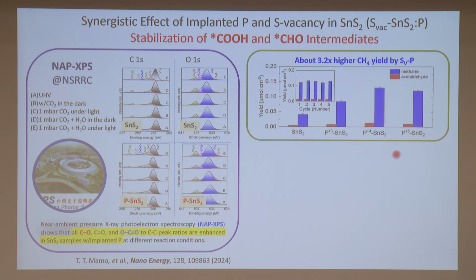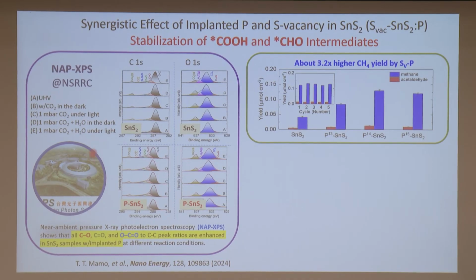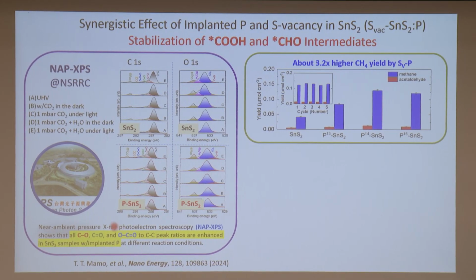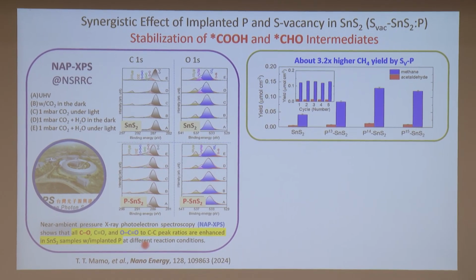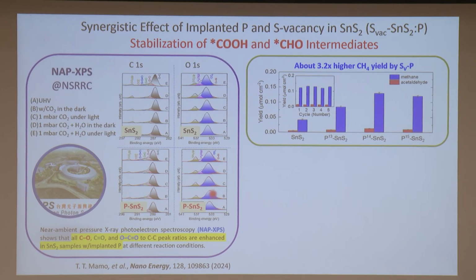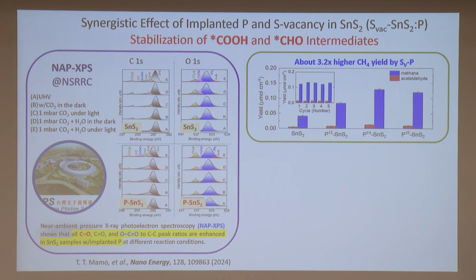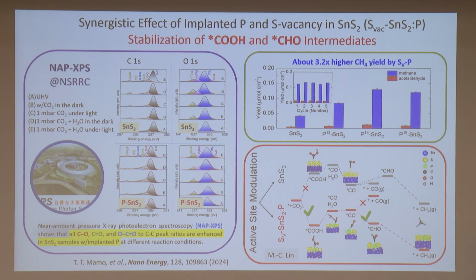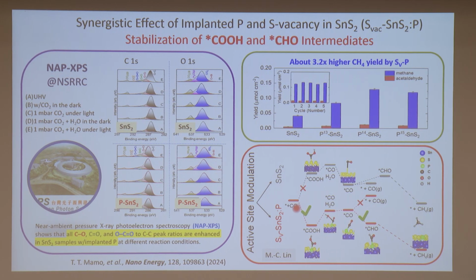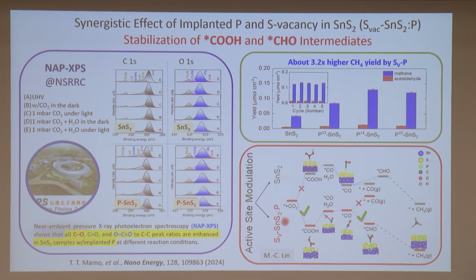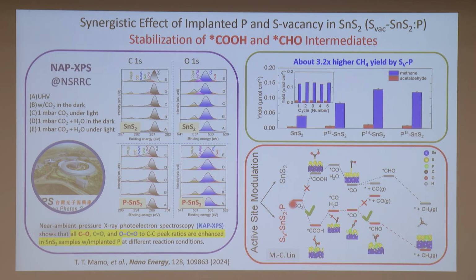To understand what's really going on, we have tried a few different methods. So for this tin disulfide case, by the near ambient pressure XPS in the NSRRC, what we learn here is with the dopant, we can increase the binding of CO, COO, and so on. So it's effectively a direct evidence of the stronger chemical bonding of the material and the CO2. And also energetically, if you do without any doping, it's actually an endothermic process. However, if you do doping, you can make it into exothermic. So you can transform to an intermediate state, and this intermediate state, after a few more processes, we can get the end product, CH4. Okay, so these are all very helpful information.